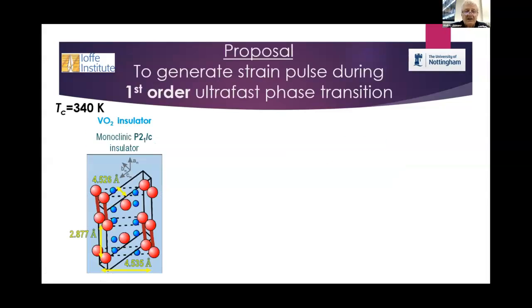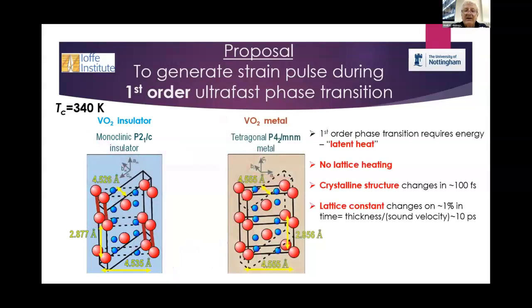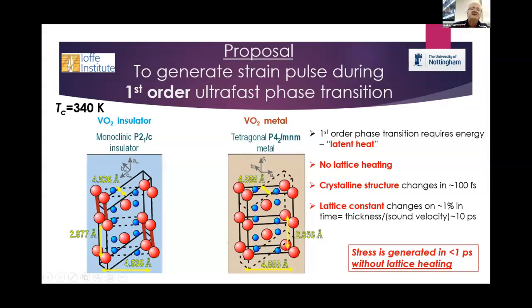Vanadium dioxide is a very well-known material. At room temperature it is in monoclinic phase and is an insulator. In equilibrium, at around 60 Celsius it transfers to metallic phase. But it is also known from the first works by Cavalieri that if we excite the system with a femtosecond pulse, it transforms to metal, and the structure becomes tetragonal. So for us it's important that it was insulator and becomes metal, but mainly that it was monoclinic and becomes tetragonal, or rutile.